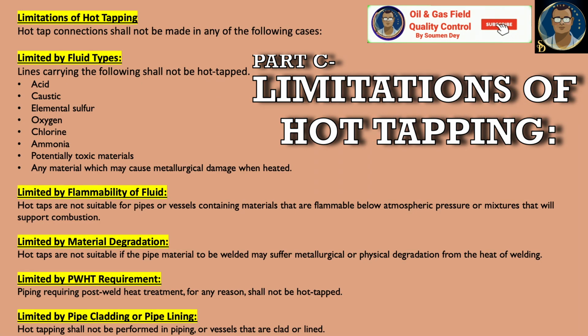Limited by fluid types. Lines carrying the following shall not be hot tapped: acid, caustic, elemental sulfur, oxygen, chlorine, ammonia, potentially toxic materials, any material which may cause metallurgical damage when heated. Limited by flammability of the fluid. Hot taps are not suitable for pipes or vessels containing materials that are flammable below atmospheric pressure or mixtures